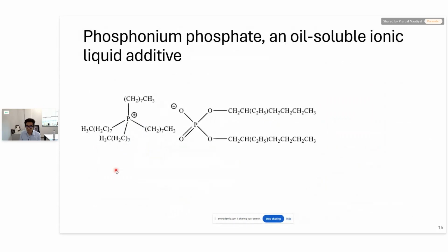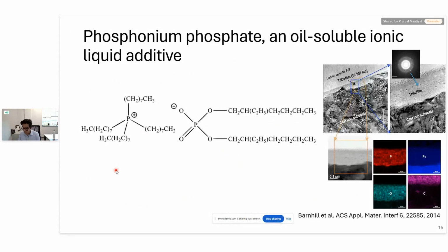This is an oil-soluble ionic liquid, which has been extensively studied. It is known to provide excellent wear resistance by forming a tribofilm in several prior studies by Dr. Jun Qu's group at Oak Ridge National Lab. It has been shown that these additives form a tribofilm composed of iron phosphate and iron oxide, and these tribofilms then protect the surfaces from wear.